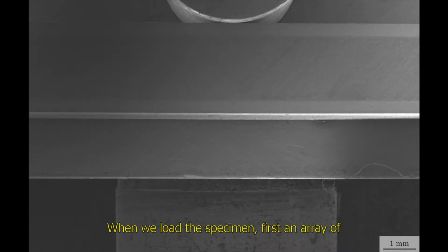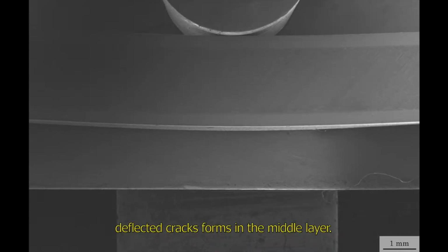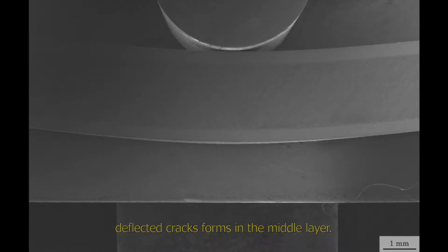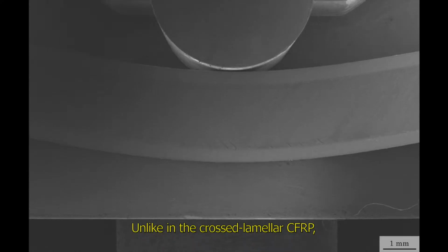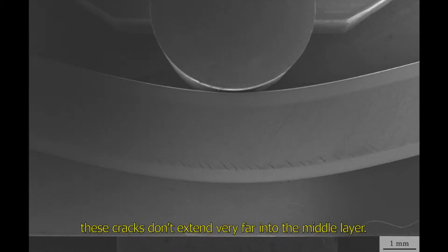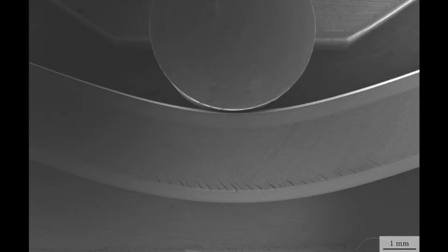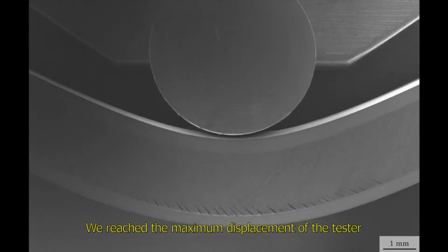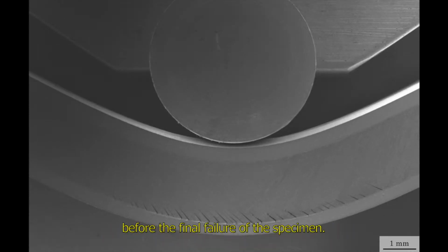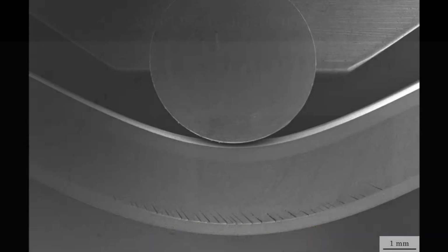When we load the specimen, first an array of deflected cracks forms in the middle layer. Unlike in the cross-lamellar CFRP, these cracks don't extend very far into the middle layer. We reached the maximum displacement of the tester before the final failure of the specimen.